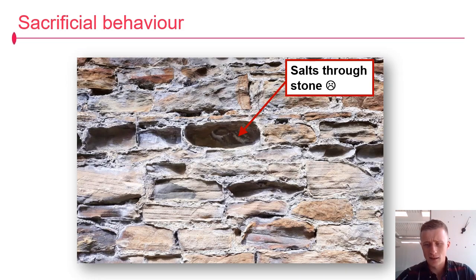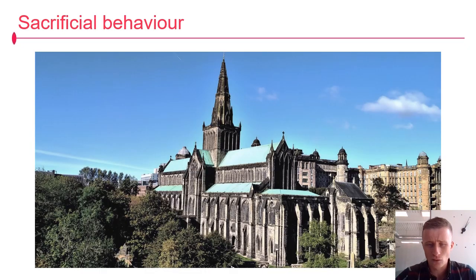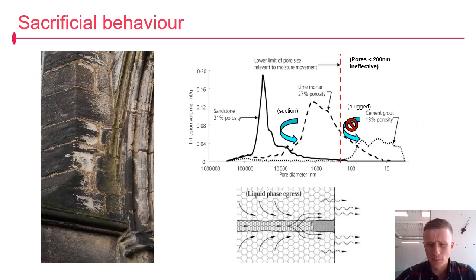Now, the reverse weathering process is why cements and other modern materials cause such damage. The salt evaporation is forced into the stone masonry unit, where the salts are then deposited and you can turn it into mush. Okay, we've seen this at Glasgow Cathedral. What you've got here is a pore size distribution spectrum, again, of three materials in this wall. So you've got your sandstone on the left, that's your coarse pored unit. You've got your traditional lime mortar from the back of the bedding joint, that's your fine pore, and you can see there's a distinct difference in pore size, so it's a very effective poultice for pulling the water out of the stone into the lime.